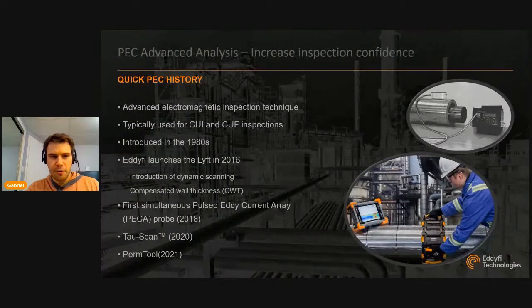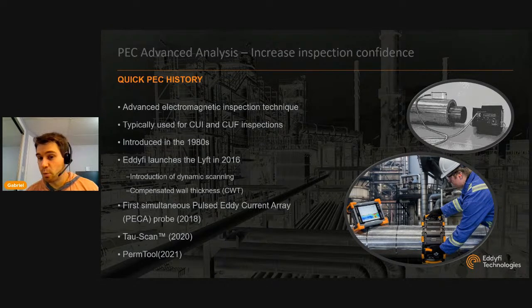Quick PEC history. So pulse eddy current is an advanced electromagnetic technique. Although it shares part of its name with conventional eddy currents, the working principles are very different. We use a magnetic pulse to magnetize the bulk of a carbon steel or cast iron component. Then we listen to the decay of the eddy currents to measure the remaining wall thickness. So instead of finding cracks or small defects like conventional eddy currents, we're looking for large generalized corrosion defects hidden under layers of typically insulation or fireproofing. It's why the technique has been used since the 1980s as a screening tool for CUI, CUF.